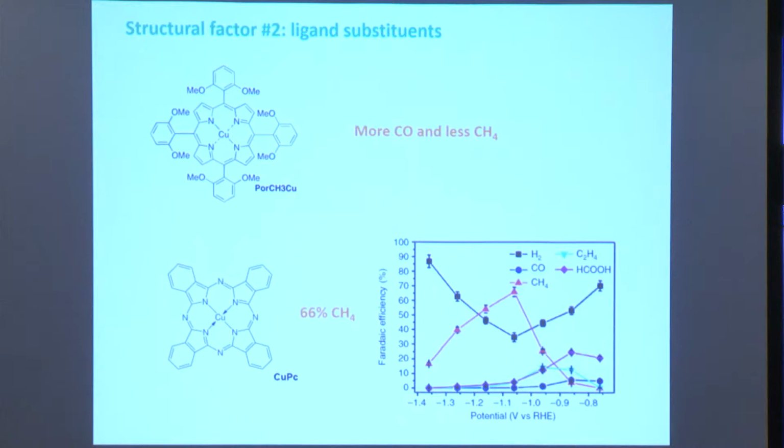So at that time, one question that came up for us was, what were the catalytic sites doing this carbon dioxide conversion, right? We looked at the catalyst before the reaction, and then we looked at the catalyst after the reaction, and we found that the molecular structures were still intact after the catalysis. It was verified by, for example, UV-Vis, fluorescence, mass spec. We still find the same complex structure. So that led us to the conclusion that the molecular structures are the active sites doing this reaction.